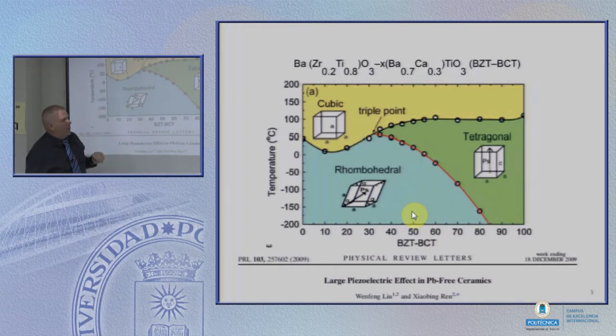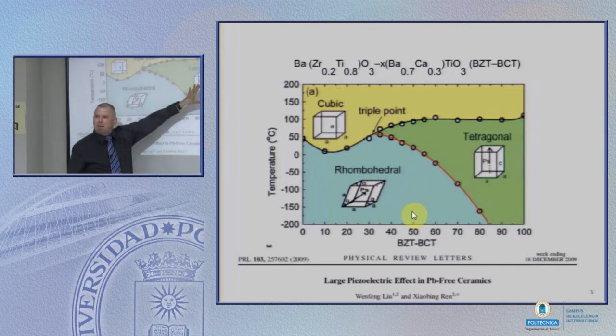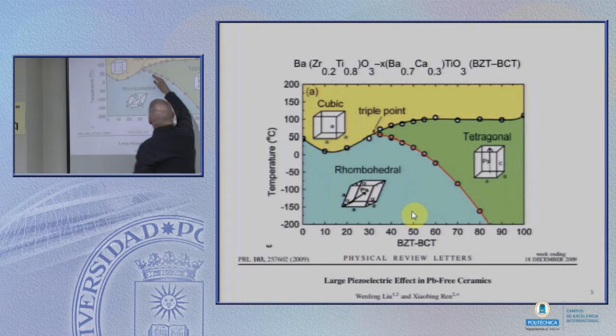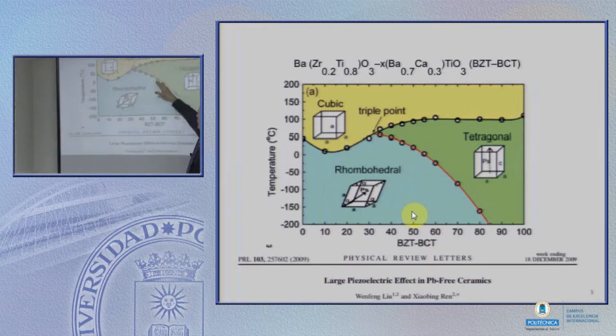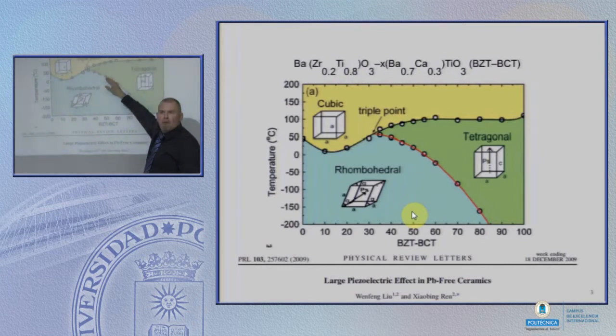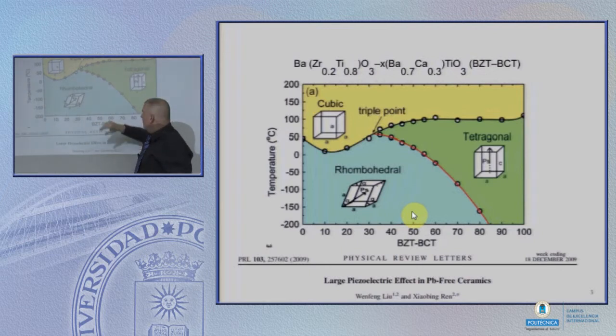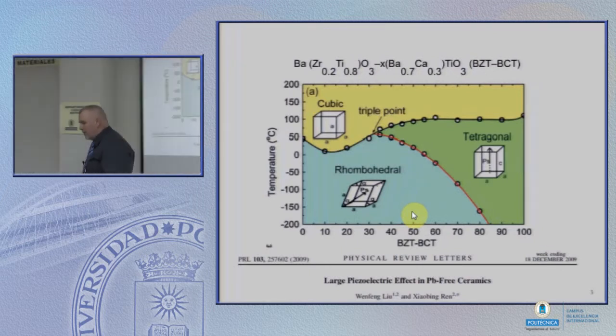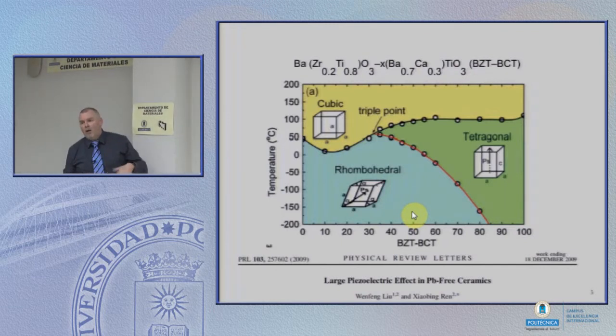And the best performing materials, the PZTs, for example, have a similar arrangement, a rhombohedral and tetragonal next to one another with cubic above. And usually at this boundary, which in PZT is very vertical, but usually near this boundary is where you see the best performance of these materials in terms of piezoelectric properties, for a number of reasons. Okay, so this was produced in 2009. We had Xiaobing come to our laboratory and meet with our students.